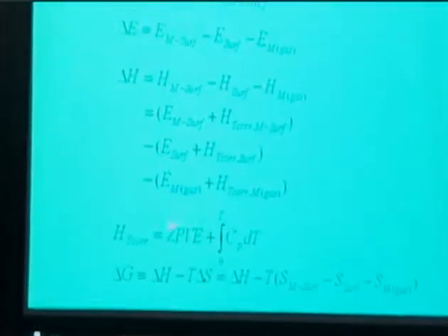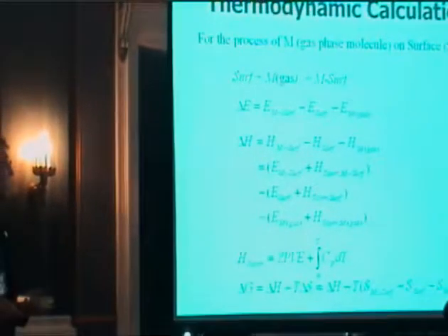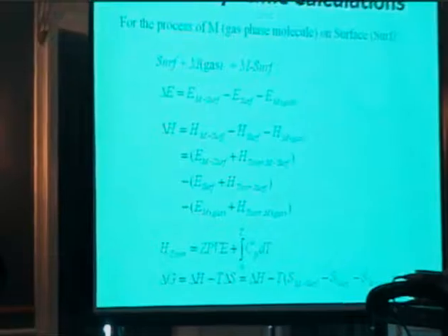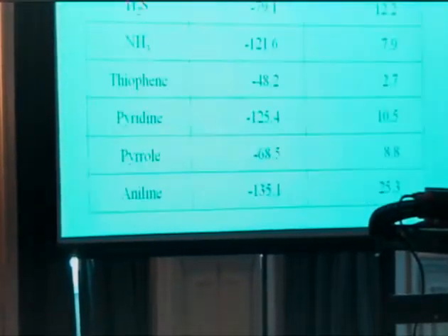Quite often, this zero-point vibrational energy is neglected in doing thermodynamic calculations based on DFT, but what I'll show you in just a minute is that this is a very important term, and if you neglect this, you can actually generate considerable errors. The other term that is commonly neglected is the entropy term, whereby we normally assume that the entropy loss upon adsorption is 100%. Again, what I'll show you in a little bit is you can't always do that, particularly for larger molecules, so we have to be concerned with this entropy term.